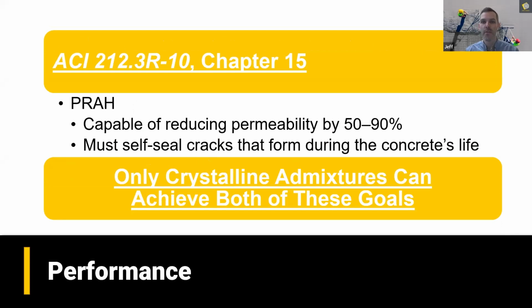Now, Chapter 15 further gives some performance guidelines on choosing a PRAH as part of a waterproofing system. In particular, it recommends that the product should have a demonstrated ability to reduce water permeability by at least 50%, and upwards of 90% and more have been reported using high hydrostatic pressure standardized testing. It's also important to make sure that product has a demonstrated ability to self-seal cracks during the life of the concrete to make sure that protection is complete and continuous. And reviewing Chapter 15 and its guidelines in their entirety, it becomes obvious that only a crystalline admixture is able to achieve both of these performance goals.